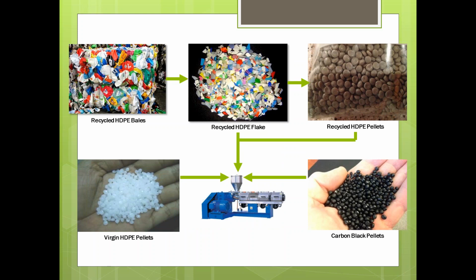So after that entire recycling process, we do a lot of quality checks on things like density, stress crack resistance, melt flow rate, moisture content, like I kind of mentioned. And we really try to get a good sense of what that recycled content is at from a performance level. When we go through those quality steps, they then get shipped to our plant, and it gets blended with a variety of different components. So you can kind of see here the typical components that are utilized in an extruded blend of recycled plastics for the pipe material itself.